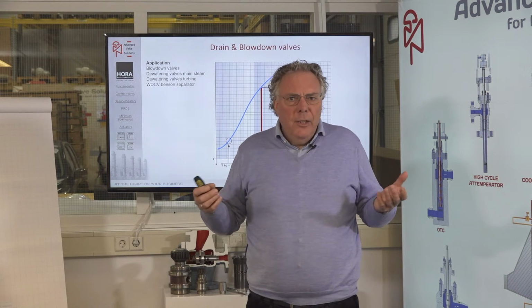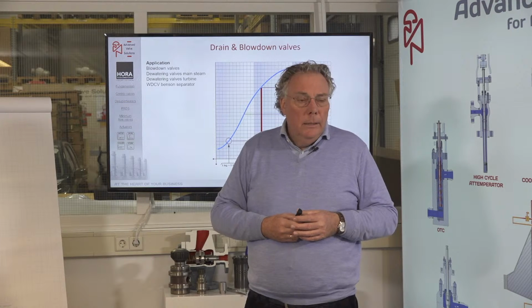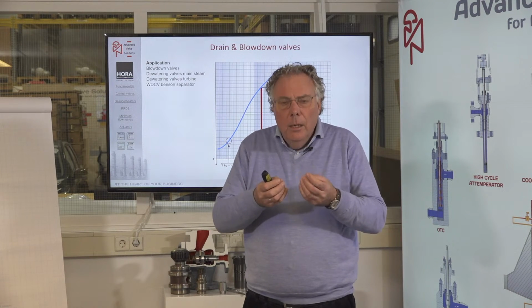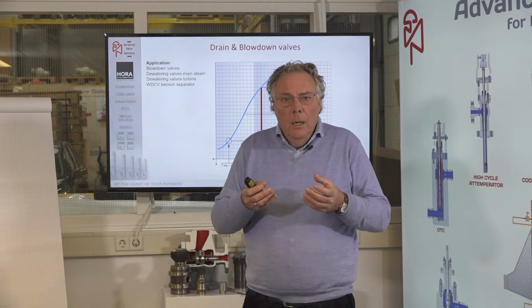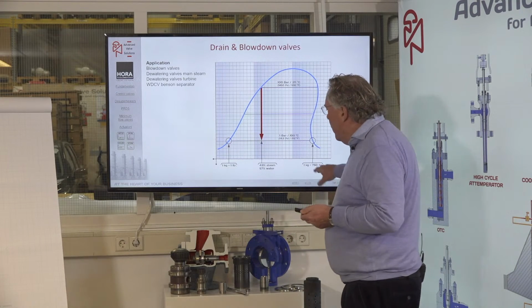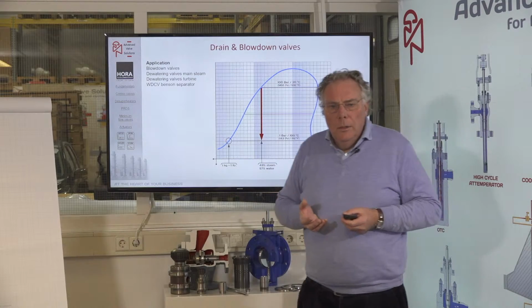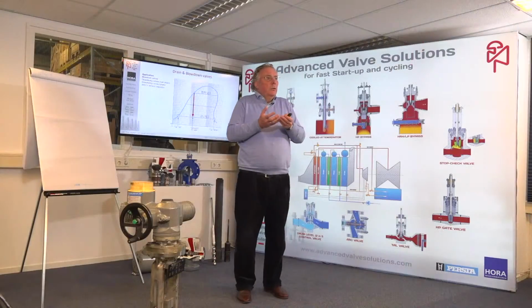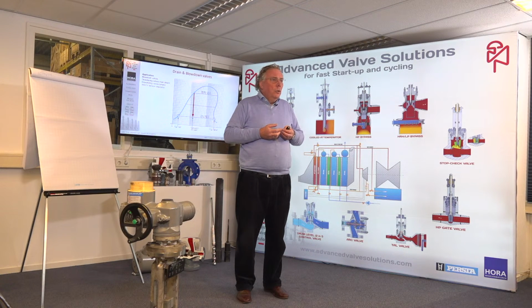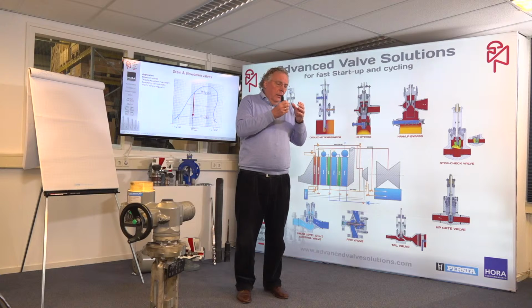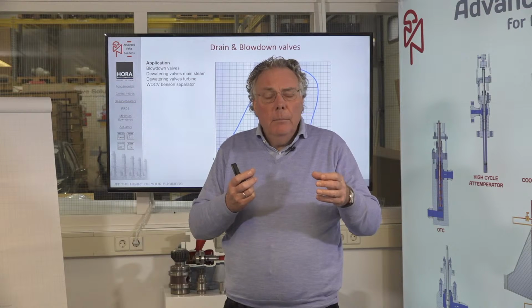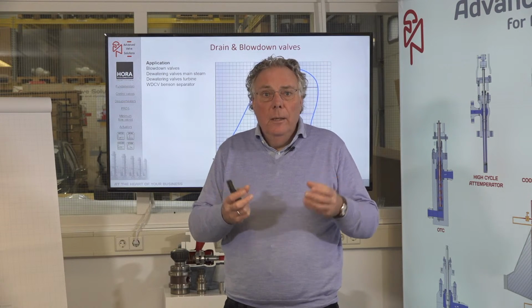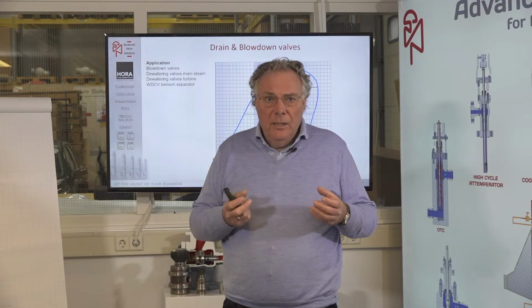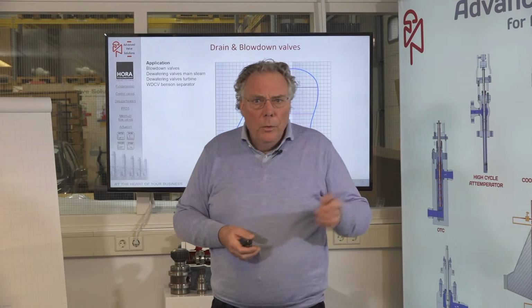That flashing process basically is harmless. It is like opening a bottle of sparkling water. You see that bubbles come out and you get a water-steam mixture. But the problem is that the water-steam mixture has a much higher volume. So that 1 liter of water where you start with is now transferred into, let's say, 300 liters, including 55% of water droplets. And when that is done in a 1 inch by 1 inch valve, my entrance velocity is a meter, my outgoing velocity is 300 meters. And you can imagine that if I have water droplets at 300 meters a second, that is eroding away everything.